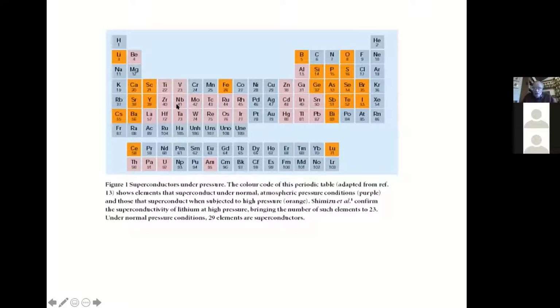And you see that actually well over half of the elements are superconductors. And of course, that's a much higher percentage than you find in intermetallic compounds in general. But of course, what you can say about this is that the ones that become superconducting under pressure, in fact, are usually not in the crystal structures that they are found in at ambient pressure.